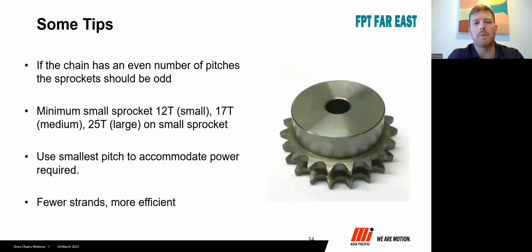Okay, then a couple of tips. So if you've got chain that's an even number of pitches, you want to use a sprocket with an odd number of teeth. And this combination of a sprocket with odd and the chain with even helps to increase the overall lifetime of the drive. And I won't go into too much detail on why, but that's just a rule of thumb or a nice thing to do. Okay, typically we don't go smaller than 12 teeth.